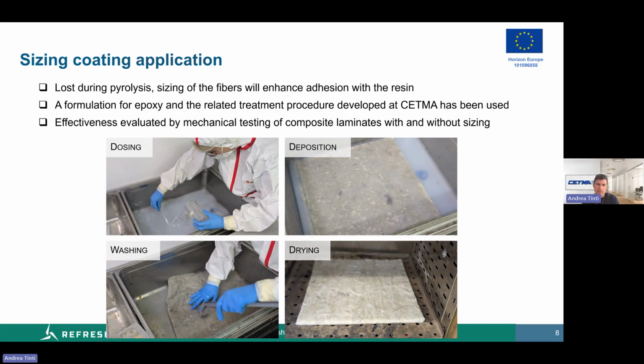Well, then the possible application on the recycled mat of a sizing coating has been studied. The sizing of glass fibers, of course, has been lost during the thermal treatment, and it could be useful in enhancing adhesion with resin in new composites. We used a formulation for epoxy and the related treatment procedure at laboratory scale, and the effectiveness of this treatment was evaluated by mechanical testing of composite laminates manufactured with and without the sizing applied.